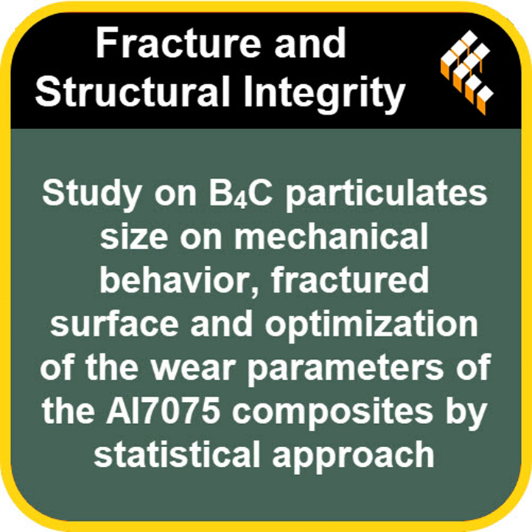And importantly, nano B4C also helps refine the grain structure of the aluminum itself. This is a well-known strengthening mechanism. It relates to something called the Hall-Petch relationship. Hall-Petch, right. That basically says smaller crystal grains make the metal stronger. Exactly. Smaller grains mean more grain boundaries, which act as barriers to dislocation movement, making the material harder to deform permanently. So nano helps on multiple fronts for strength. Okay, that makes sense. Smaller grains, stronger material, nano seems better.